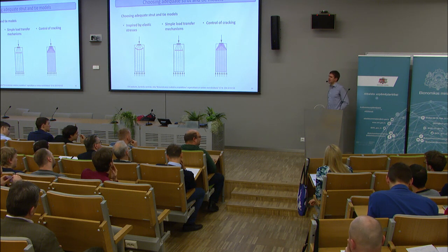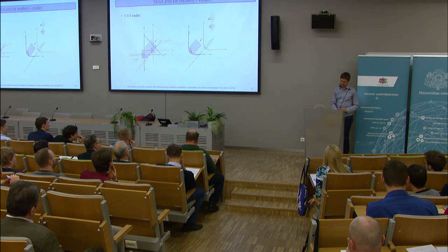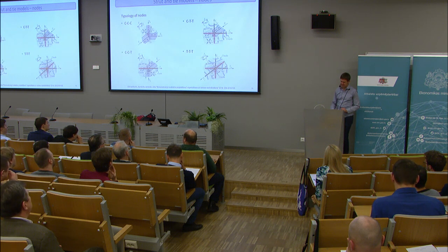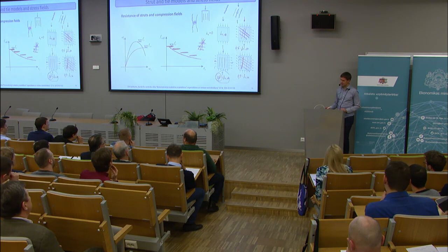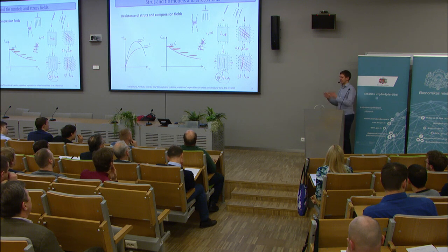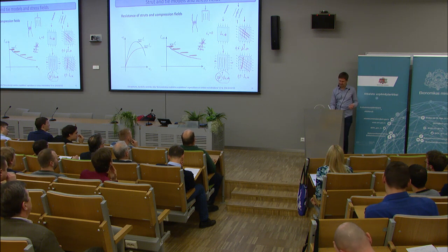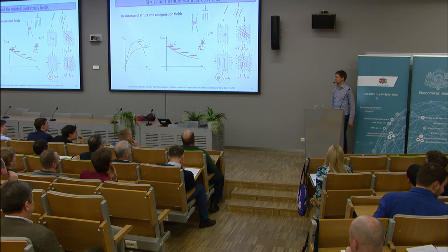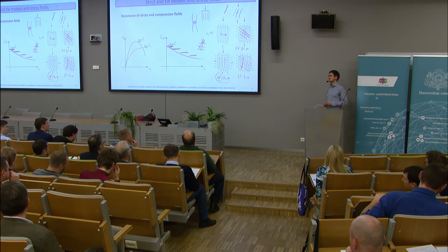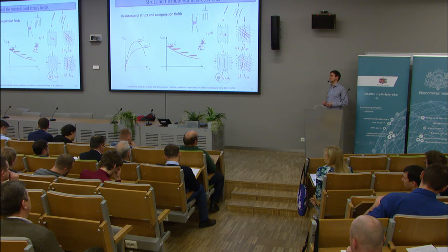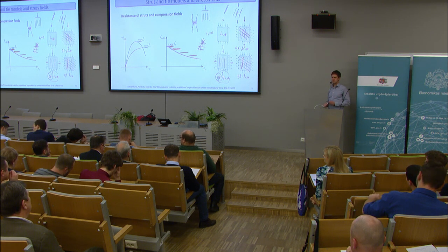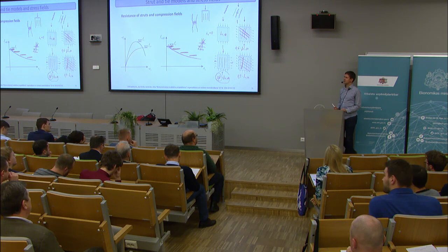Yeah, if you can show that the transverse strains are not high, then you could use the exact formula for the transverse strains. And actually, even in Eurocode, there is a sentence that if you know better, you can use a better formula. So you can use the Vecchio and Collins formula and calculate the lateral strains, say that they cannot be higher than that, and then calculate your reduction factor, which probably will be quite close to one. So would you be able to calculate these strains if you know the transverse tensile force? You provide reinforcement, you calculate the stress in the reinforcement, and you could calculate the strains in this way. Yes. Okay. Thank you.